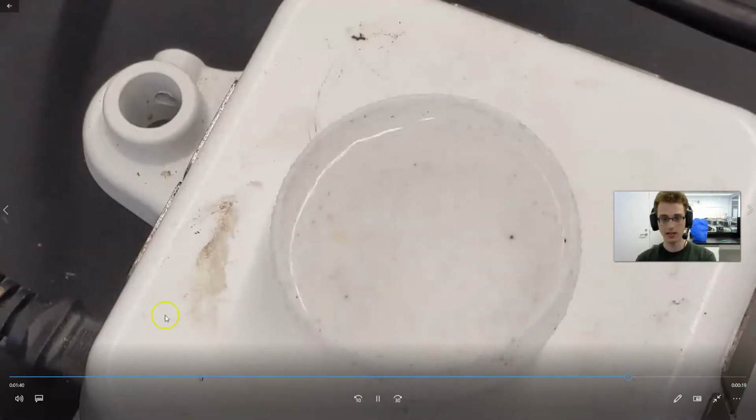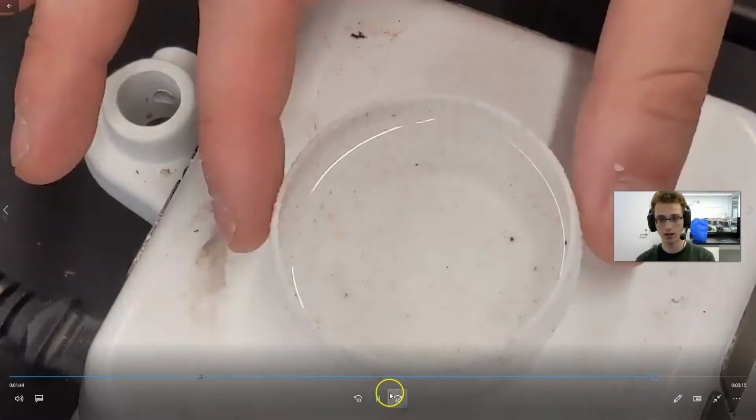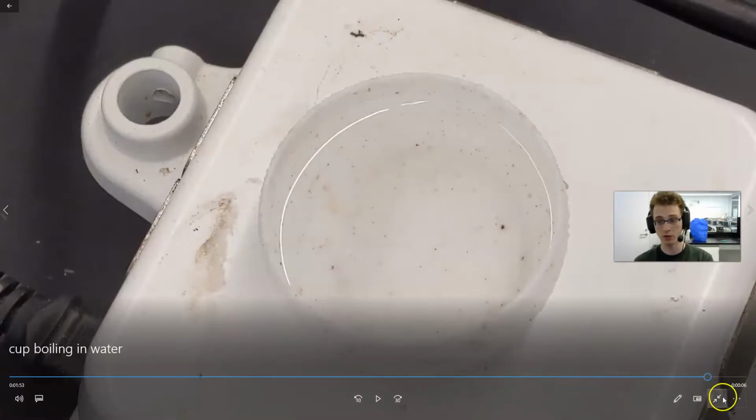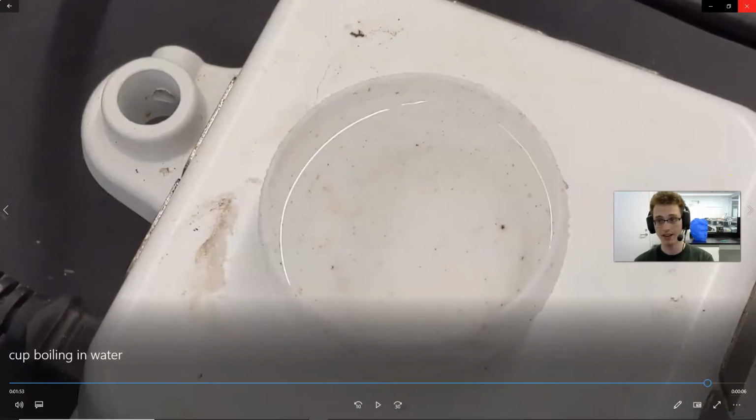So this is kind of an experimental roll. You might have noticed these little splotches on the parts. That's because it was contaminated a little bit with iron. I've heard that this problem has been fixed. So if you want to try this yourself, it's actually probably one of the easier materials to work with. You don't need as many consumables, and it's not as high temperature as copper if you just want it to be porous. So I absolutely recommend you try using this material.